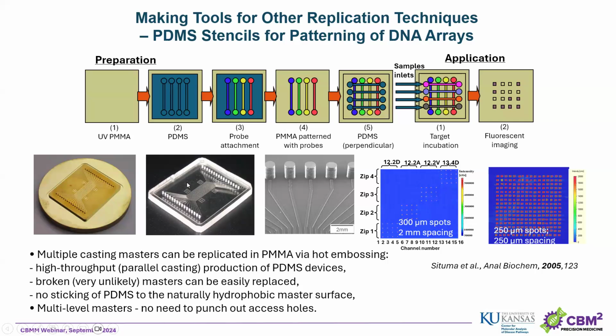These are pretty much unbreakable and they can be easily replaced. Since PMMA is hydrophobic by nature, the PDMS doesn't really stick, so you can use them over and over again without worrying that something sticks to the surface. And as shown on this SEM, we can do multiple heights and multiple size ranges, which means we can also do those posts that after you cut your PDMS become holes. So instead of having a flat piece of PDMS that you have to punch, in this case, 32 holes, this gives you pretty much a ready to use PDMS device.